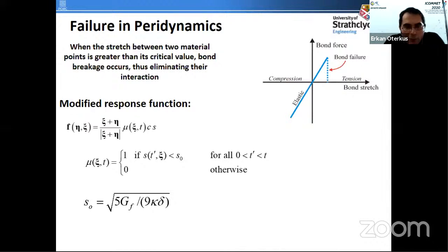So far, I didn't talk about failure in peridynamics. It's really straightforward to define failure in peridynamics. What we do is we always check the stretch of two material points. And once this stretch exceeds a critical distance that we call critical stretch, then we just break an interaction. That means that our force is basically dropping to 0.